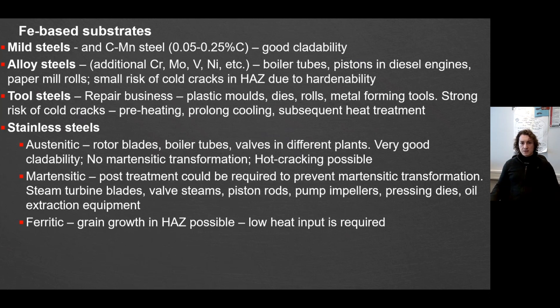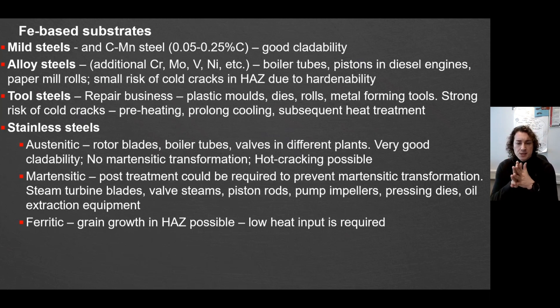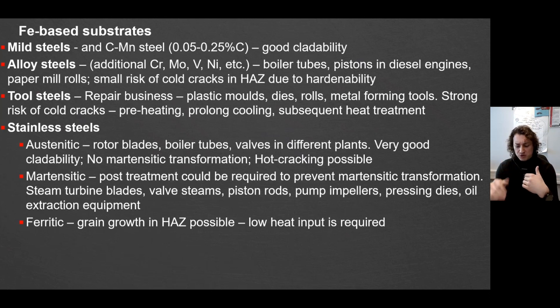Martensitic stainless steels, in contrast, will almost always undergo martensitic transformation — especially 400-series steels. Your hardness values grow extremely; you can get over 50 Rockwell even with materials like 420 steel, and there is of course a high risk of cracking. You should think about how to prevent this martensitic transformation, primarily through post-treatment methods. The last group here is ferritic steels, which may have issues with grain growth that can lead to cracking. If you work with ferritic steels as a substrate, you always have to ensure that you do not put too much heat input to the surface. Knowing how differently you should behave with each steel group, you can avoid a lot of mistakes in your process.